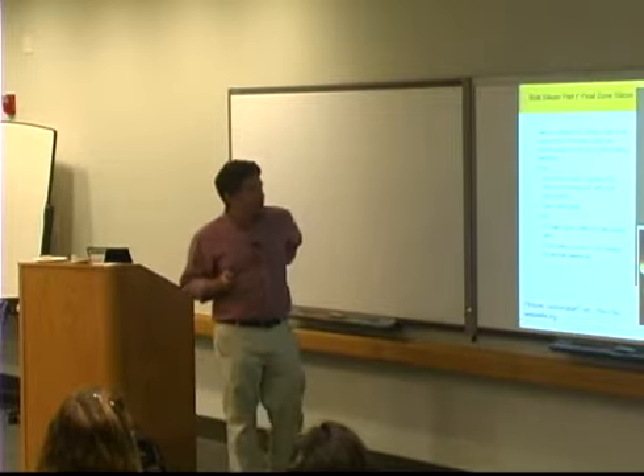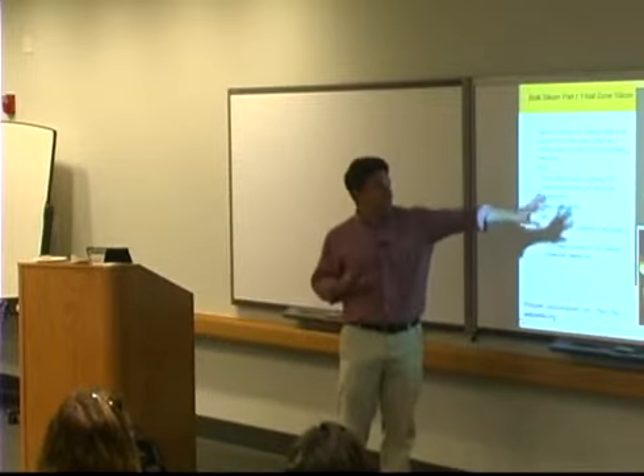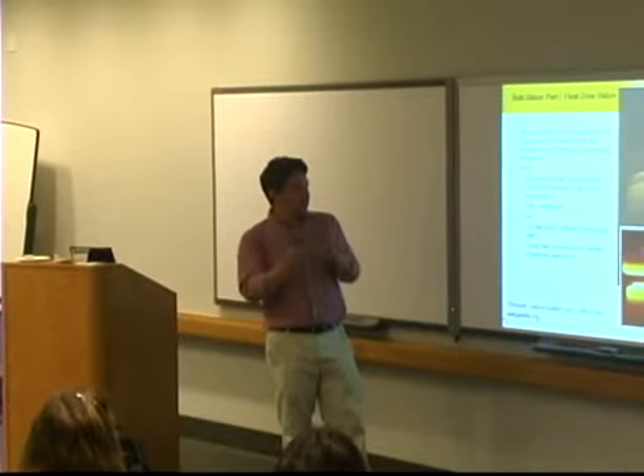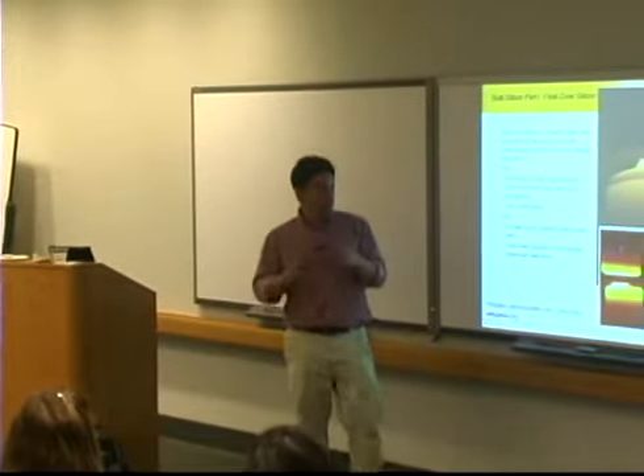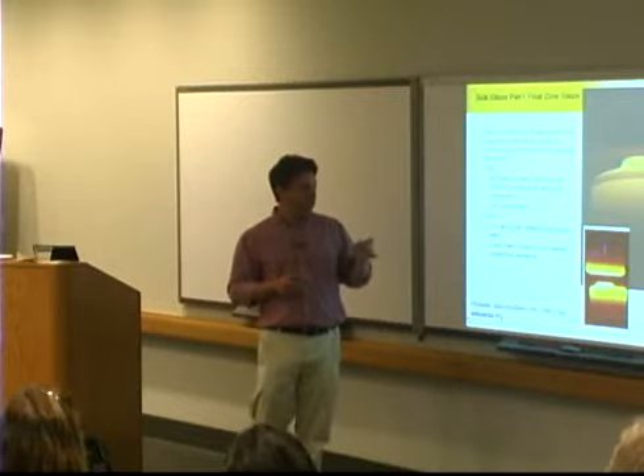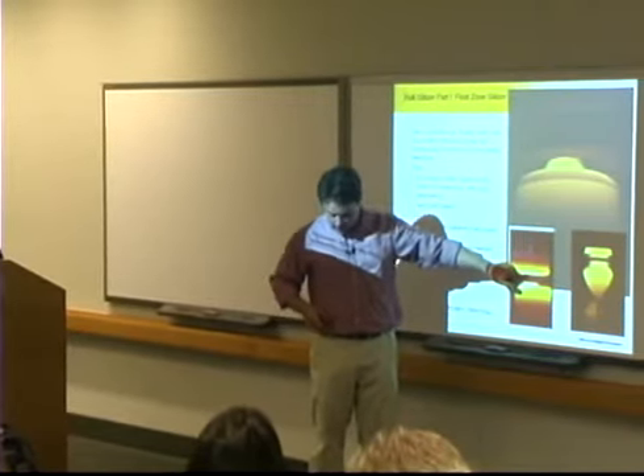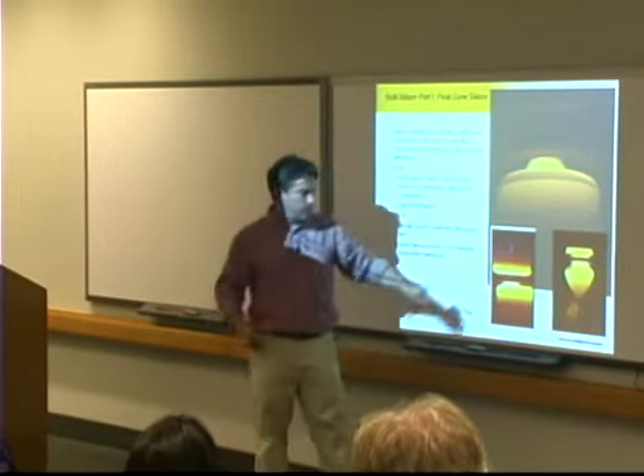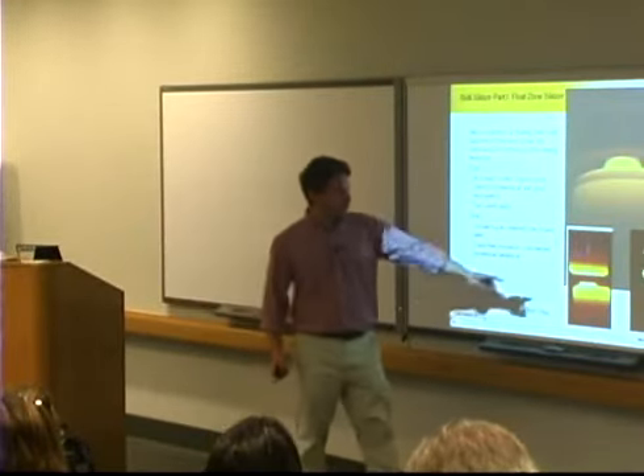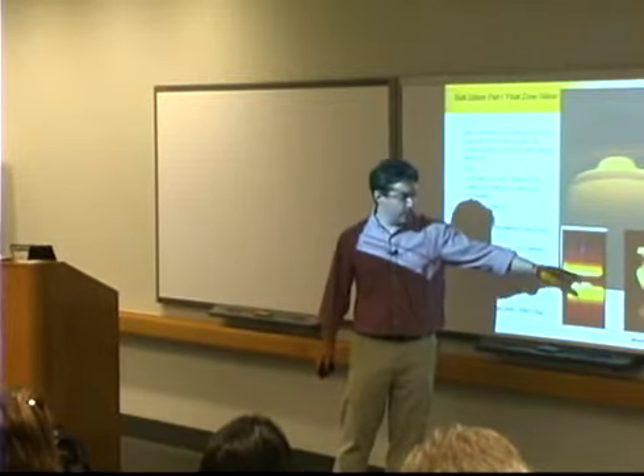Okay, so moving on to bulk silicon. This is the float zone method, and I won't say too much about it. It's completely awesome. You start with these highly pure polysilicon rods, so they've got tiny little grains, and you basically have just a single electromagnetic coil, just a single turn, and there's a hole in it, maybe about this size. And what you do is you bring the silicon down, and you have to do a little bit of preheating to get the silicon to couple inductively to the high frequency RF magnetic field. But once it does, it becomes kind of self-sustaining. It gets conductive enough, and you get actual melting of the silicon.